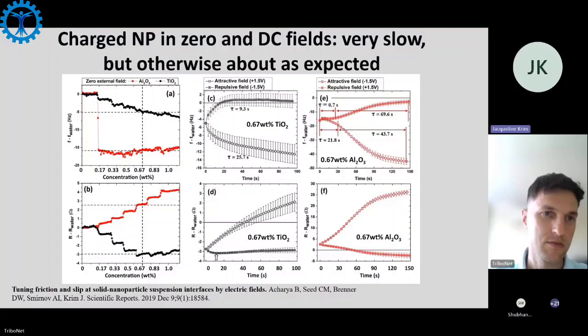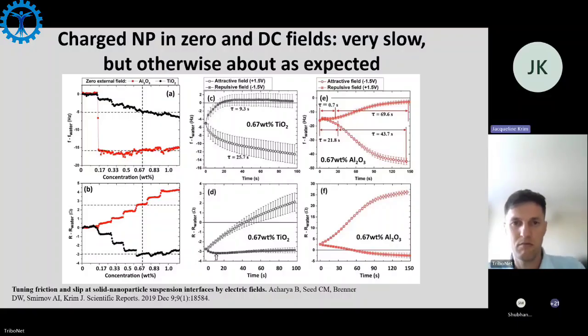Titanium oxide, the black, negatively charged, the frequency doesn't drop as much. Remember, if this were superfluid helium, it wouldn't drop at all. Alumina, it did, a positive charge. Turning on an attractive field caused them to drift in opposite directions, both the damping forces and the frequency. So we're expecting opposite behavior and we're observing opposite behavior.